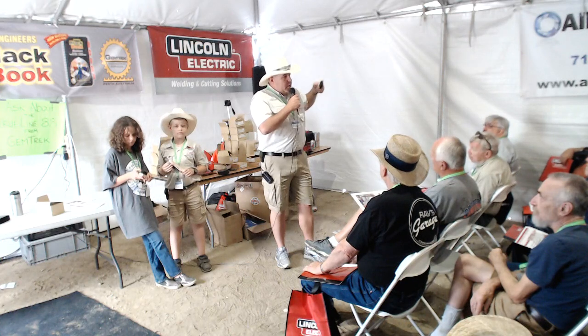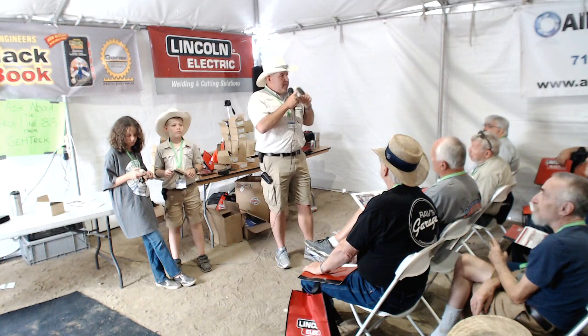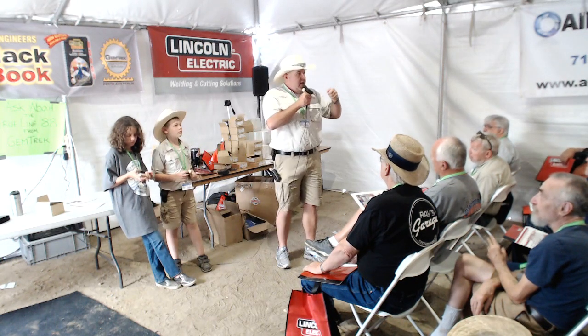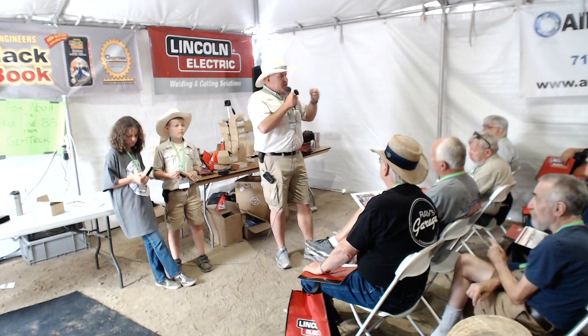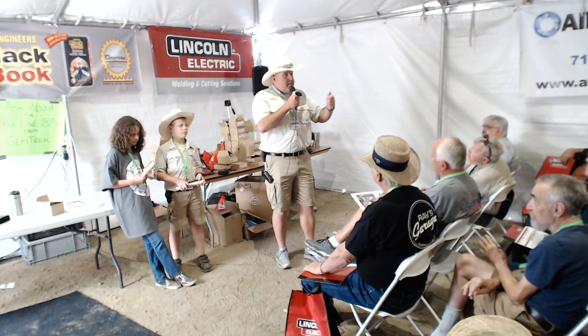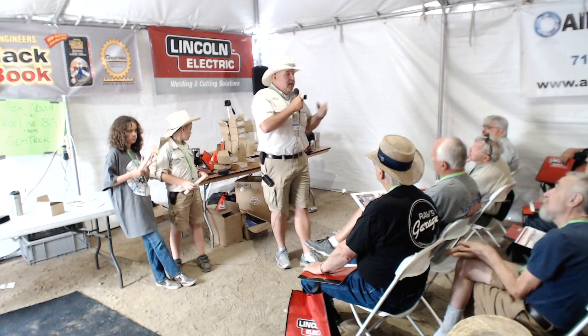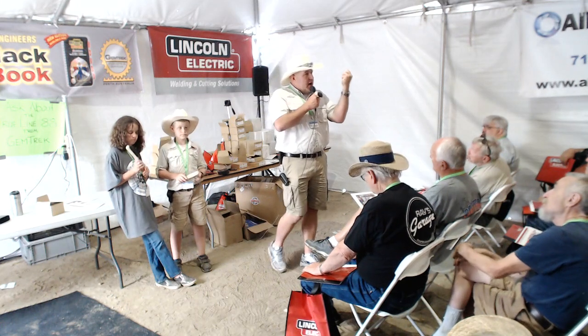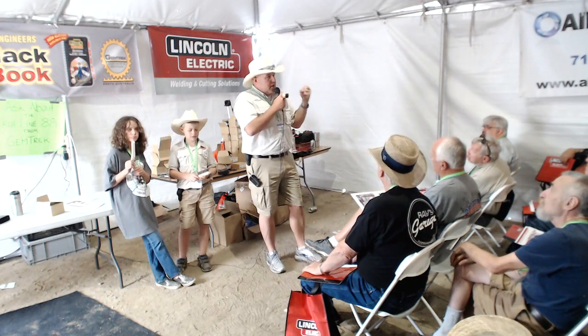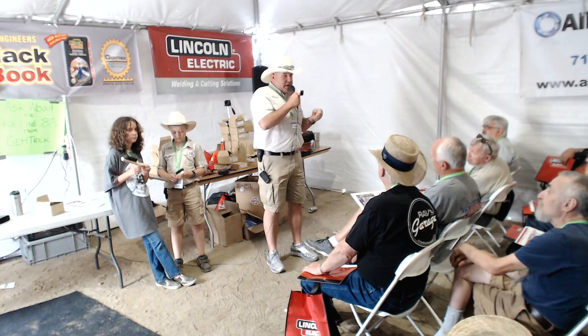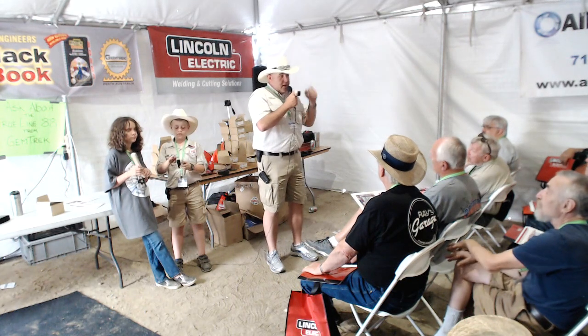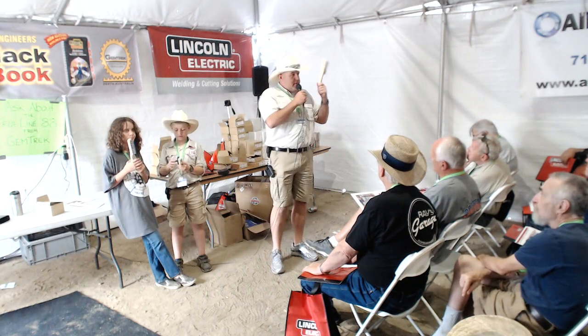If we start brushing the aluminum with this thing, that flakes off. And aluminum's soft, so we put scratch marks in it and scratch the rust down into the aluminum. Then we make a molten puddle out of it, and we encase that iron oxide in the aluminum. That's called a discontinuity. And what starts at a discontinuity? The crack. Stainless steel doesn't do that.